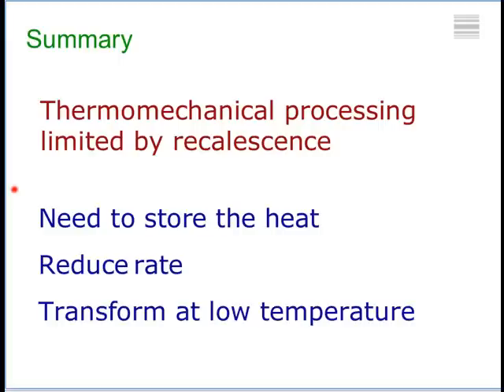So just to summarize, thermomechanical processing is limited by recalescence. That means the heat of transformation actually heats up the steel so that we are not actually undercooling below the equilibrium temperature. If you put a thermocouple on the steel, you will see the temperature actually rise as the material tries to cool, because the heat of transformation can't be dissipated fast enough. So to get to a finer grain size, we need to store that heat of transformation inside the material.